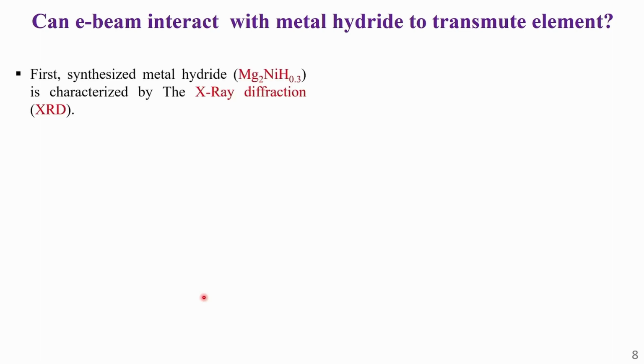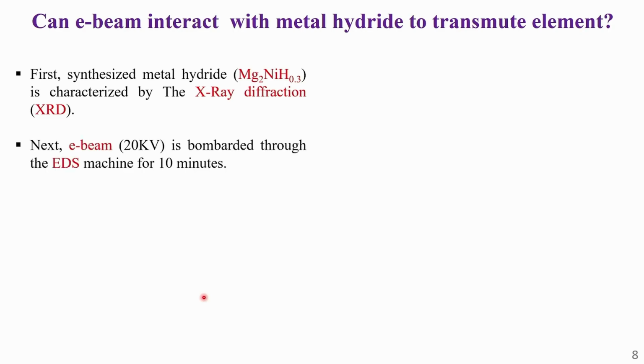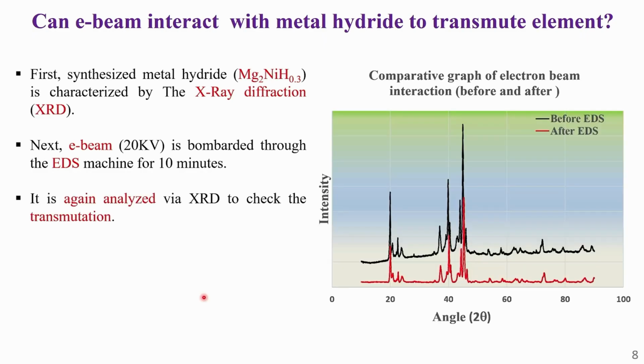We synthesize a metal hydride sample of magnesium nickel hydride as a control and characterize it using XRD. Now the metal hydride sample is exposed to a 20 keV electron beam from the EDS machine for 10 minutes so as to mimic the electron interacting with the electrode sample during the elemental analysis. We then again analyze this exposed sample using XRD. This image shows the XRD results for the control sample before and after electron beam exposure.